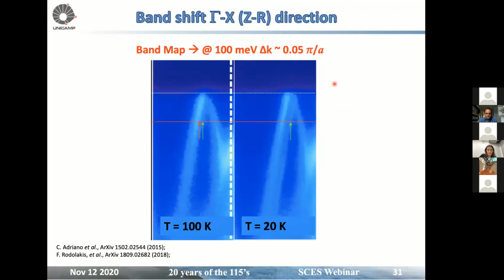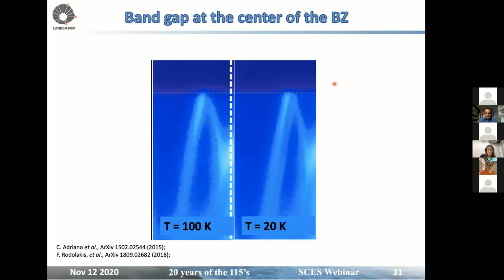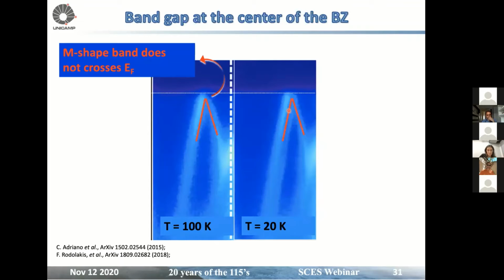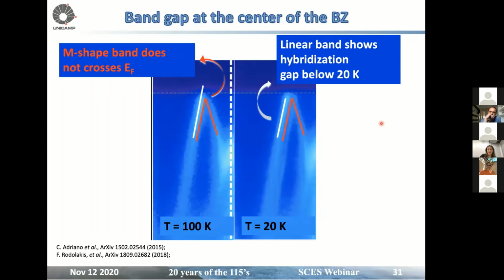But what I would like to point out here is that I call that band here the M-shaped band. And that band never crosses the Fermi level as a function of temperature. And the band that crosses is the one that does not move in k, and that I colored in white here. And that one is the linear band that shows a hybridization gap. I'm telling you the result below 20K.